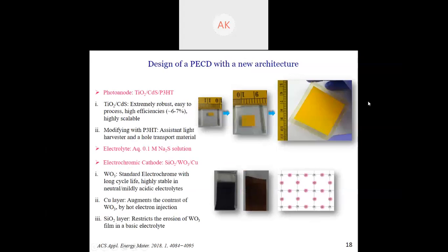So we aimed in our lab at designing a PECD with a new architecture wherein we used a TiO2/CdS photoanode. TiO2/CdS is extremely robust, easy to process, and has high efficiencies of 6 to 7%. It is also highly scalable. As you can see in the figure, we have gone up to a 5x5 cell. If you think of taking a design from lab scale to an industrial level, the first point that comes up is scaling it up. That's why we use TiO2/CdS. We have also modified it slightly with a semiconductor polymer, P3HT. P3HT is poly(3-hexylthiophene). This works as an assistant light harvester and also a hole transport material.